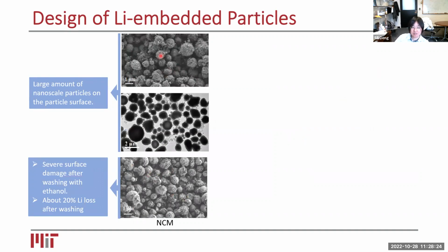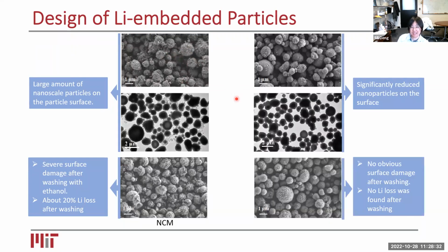Okay, so this is the current way that I just introduced. We have these lithium enriched surfaces. And this is some magic we did afterwards, where I will talk about exactly what it is. But you can see from the SEM and TEM, these nanomaterials disappear. And after we also dissolve the particles into acid solutions to see if it means that we are losing lithium, the answer is no, the lithium content stays the same as the previous case. So the only explanation is that now our lithium has been incorporated into the particles. It has diffused in and has uniform distribution with the other metal oxides. The magic we played was to use urea as an additive, 1%, 2% by mass, in the solutions.